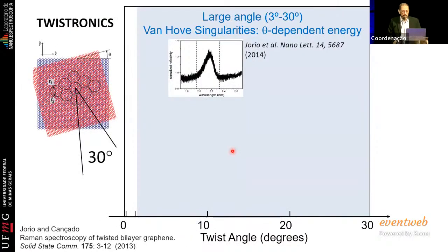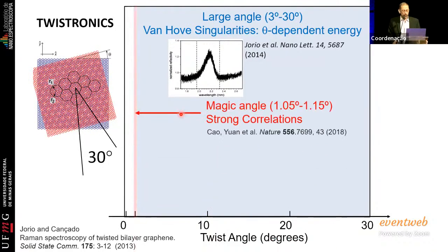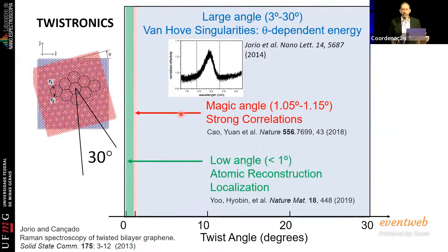Okay, so here is a summary. Graphene is hexagonal, so every 30 degrees you have a repetition of the structure. So if I plot here from 0 to 30, what happens, let's say, at large angle rotation is that you can control with the rotation the energy of absorption and reflection of graphene. If you go to this very specific magic angle, you have correlation phenomena, you have superconductivity observed in graphene. And if you go below that, you have the atomic reconstruction and the formation of the domain walls. They are called strain solitons. And you have the AA sites that are sometimes called topological defects.